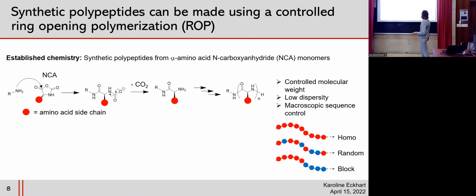polypeptide, where we have control over the molecular weight based on the molar ratio of the monomer to initiator. And we also get low dispersity, meaning homogeneous molecular weight. And this approaches natural proteins. We also are able to access macroscopic sequence control. So we can achieve homopeptides, random, and block copolypeptide sequences.